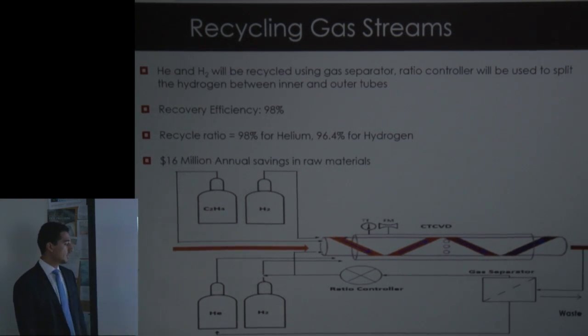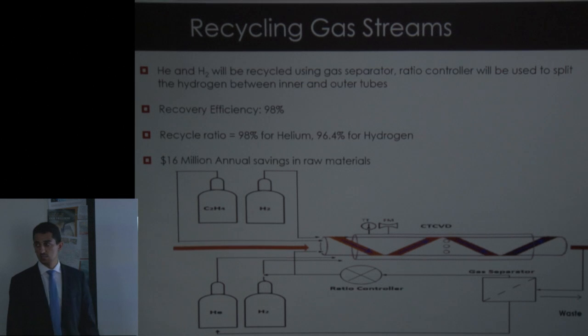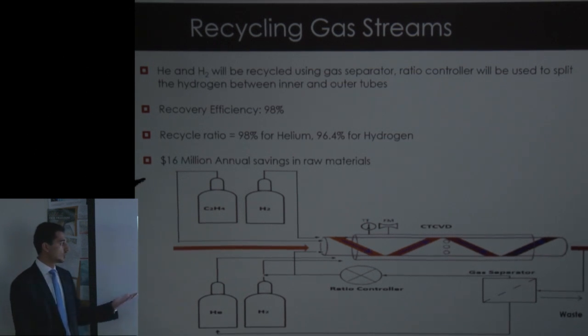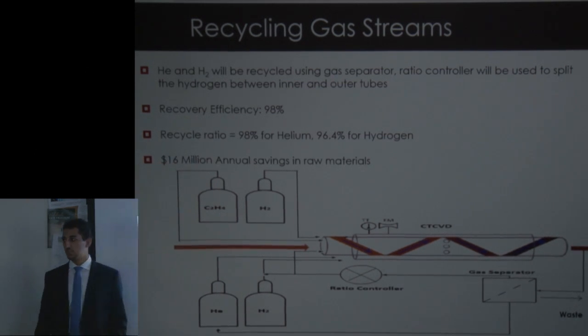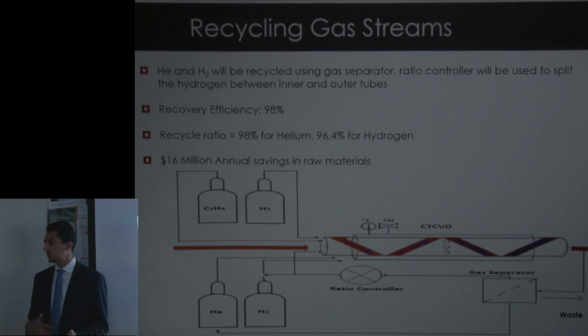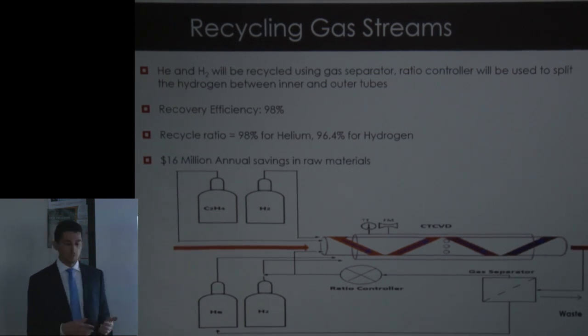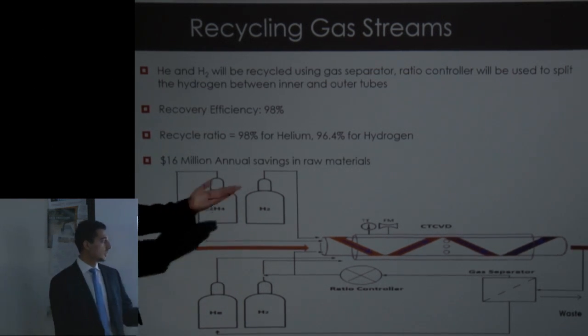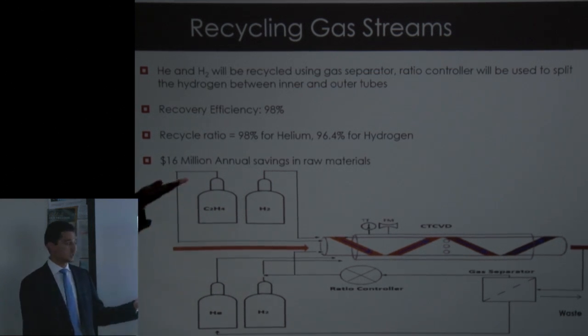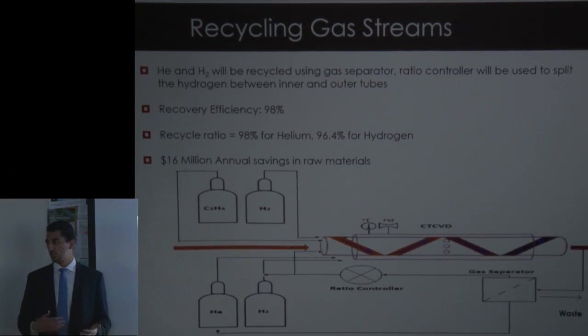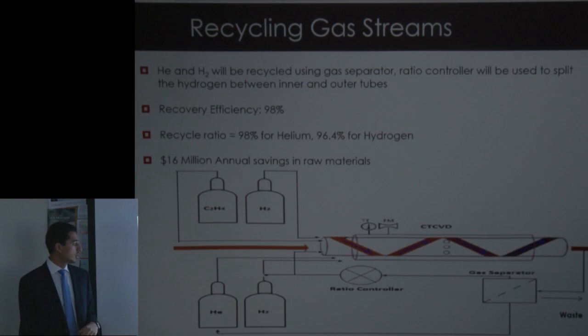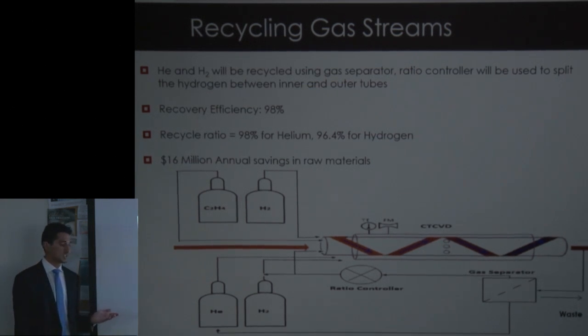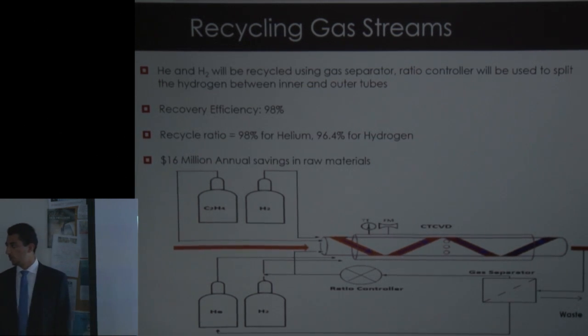So the recovery efficiency of our process is estimated to be 98%. The recycle ratio is 98% for helium, since helium is introduced in our process as an inert and it doesn't basically get consumed in the process. For hydrogen, the recycle ratio is 96.4. The 3.6% is basically consumed within the reactor. We're estimating to save $16 million annually on raw materials with this recycle.